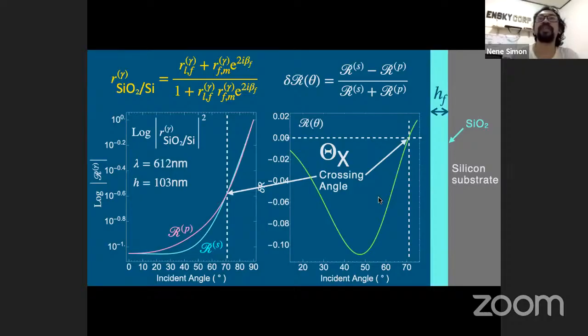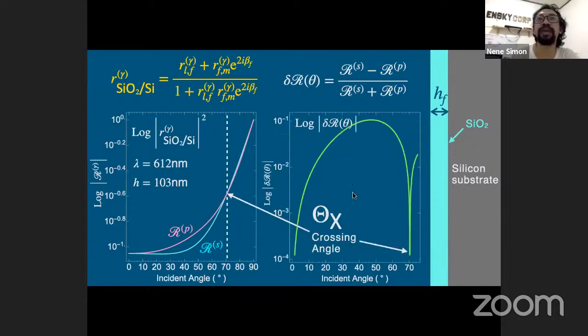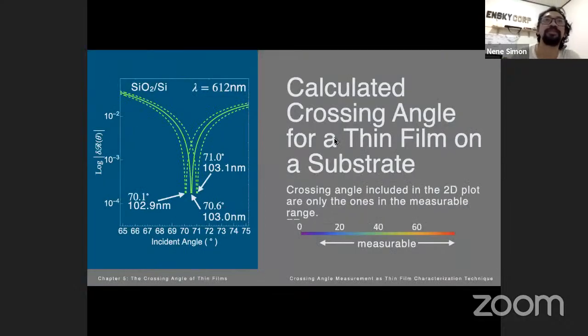And if we take the logarithmic scale, we take the absolute value of the delta R and take the logarithm, we will have this nice dip here. The dip here is the location of the crossing angle. So we calculated for the position of the crossing angle for different film thickness.